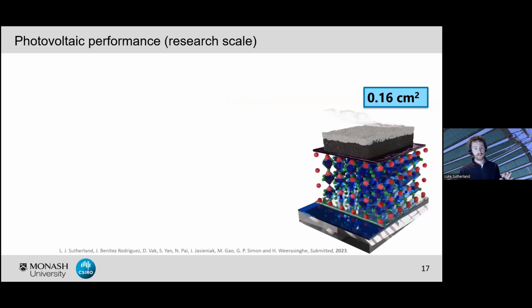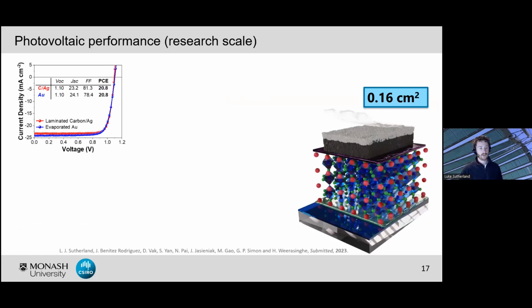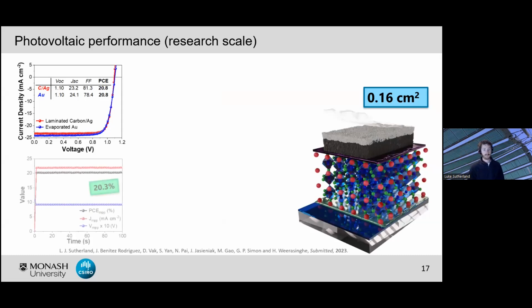All of this then translated into achieving some really great results on the research scale. So for 0.16 centimeter squared cells, we were able to directly match the performance of our evaporated gold counterparts, achieving a maximum efficiency of 20.8%. Now this was the maximum for both our laminated electrode and our evaporated gold after batches. So batch after batch after batch, these were the maximum efficiencies we were able to achieve. This device exhibited a stabilized efficiency of 20.3%.